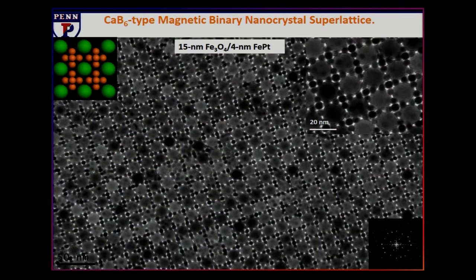What we do is we characterize the key reflections of each class, and then we use comparisons between those and the other samples. And if it's publication, or it's really important to make sure you got it right, then that one you put through the extra piece. So the amount of time it takes to do the full crystallographic study of each one is not practical for every sample, but it allows you to build up these ideas about how we organize.